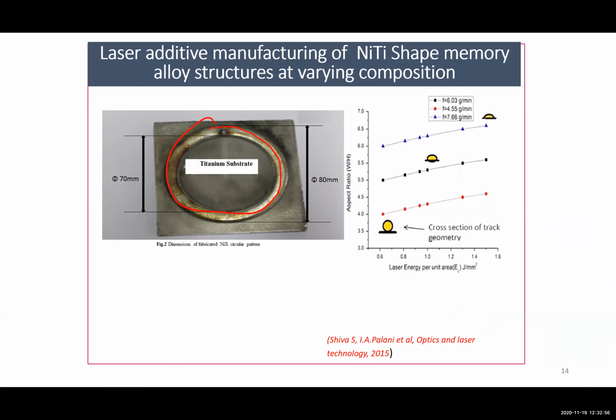But here, the major challenge I am facing is that I am starting from scratch. It is a challenging job, as I am creating a customized structure. In this customized structure, I have a titanium substrate. The major parameter which affects my structures is the wettability. In order to control the wettability, I need to control the laser energy and the aspect ratio which I am trying to employ.